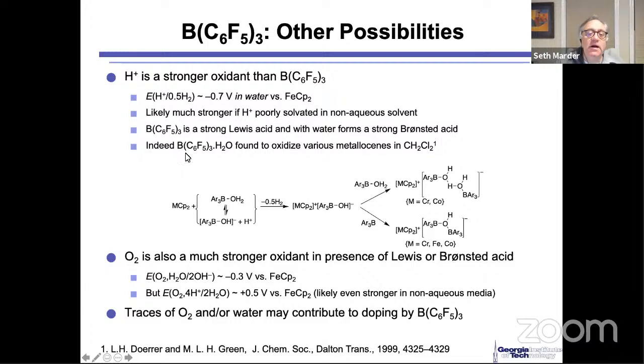So the reality is that what happens is that this reacts, and from a stoichiometric perspective, you lose half an equivalent of hydrogen. This is not to say that this is mechanistically what happens. You end up with this material perhaps transiently, and then what ultimately happens is that that reacts either with another equivalent of the water adduct or another equivalent of the triarylborane. Now, how do we know that? And the answer is because he literally isolated, characterized, and has crystal structures of these compounds. Now, which one of these anions is present in these polymers? I don't know yet.